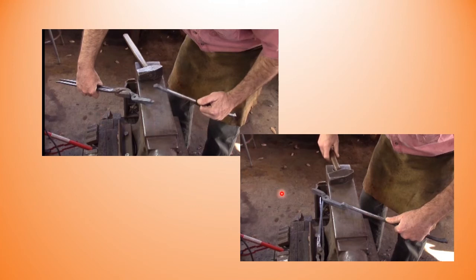You're now ready to position your pieces and conduct your weld. These photos are showing this done before the pieces are heated and I would recommend that you do the same. The name drop tong is literal. The hammer hand, in this case a right-handed smith, is holding the tongs with the piece step up. The longer piece is held in the material hand and will be fitted over the top, and with some downward pressure hold this in place. Then you can drop your tongs, pick up your hammer, and conduct your weld.